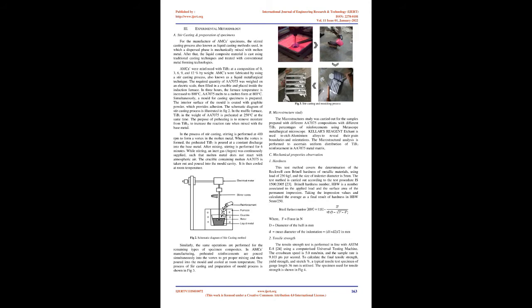AMCs were reinforced with TiB2 at compositions of 0, 3, 6, 9, and 12% by weight. AMCs were fabricated using a stir casting process, also known as a liquid metallurgical technique. The required quantity of AA7075 was weighed on an electric scale, then filled in a crucible and placed inside the induction furnace. In 3 hours, the furnace temperature is increased to 800 degrees Celsius, and AA7075 melts to a molten form.